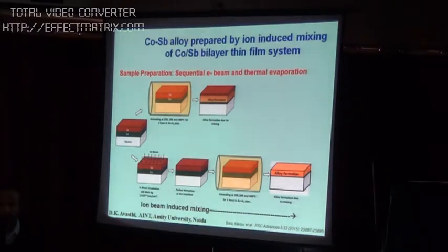I take one more case here. Here we have taken cobalt and antimony. Again, this can be done with the thermal evaporator. And then if you heat it, you get some alloy here, cobalt and antimony. But then something will be unmixed here, which is here and here. But if you do irradiation in the same thing, and then you do annealing, you get complete alloy formation. So that is the advantage.